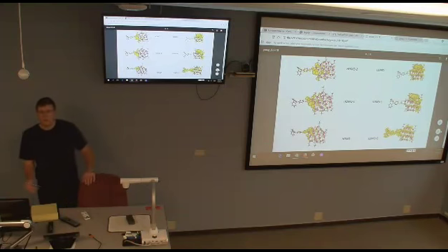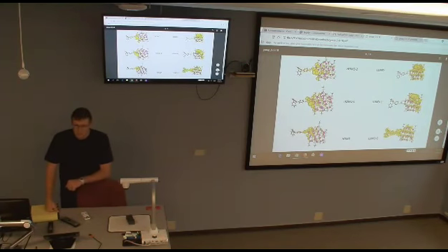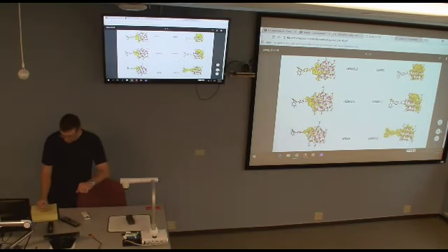And again, for the purpose of comparing with a bare dot, right? I mean, bare means without this. It's not bare; it's still covered with these amines and so on. I would suggest maybe the easiest model, which you can directly compare, would be to just take out the molecule but leave the linkage group, carboxylate, or how do you call it? Cyanide. Okay. I probably think hydrogen would be good enough. You don't need to put the methyl group on the carbon, right? So hydrogen would be good enough. So kind of create this additional ligand, not the dye, but a ligand of a different nature, not amines, but something different.